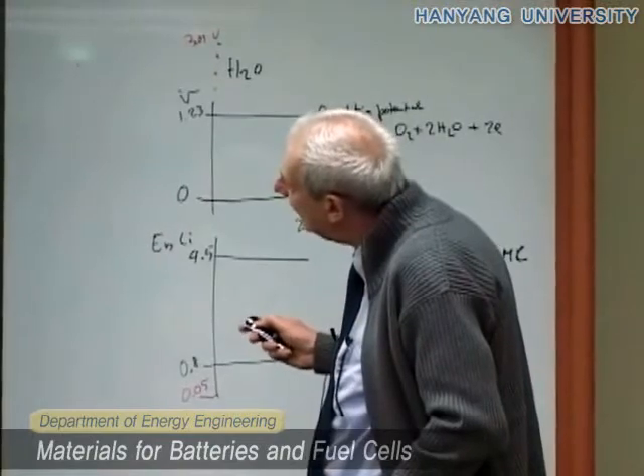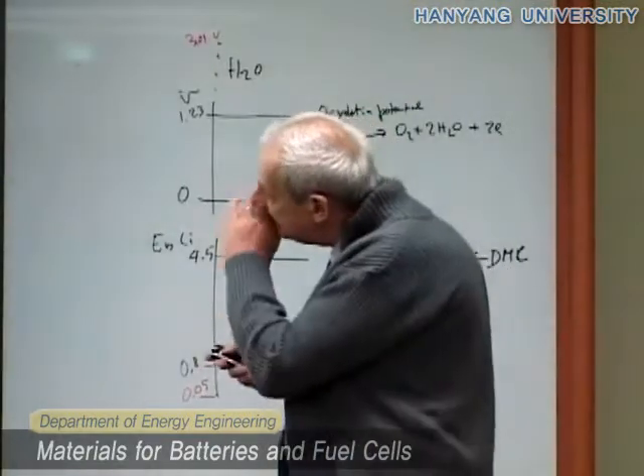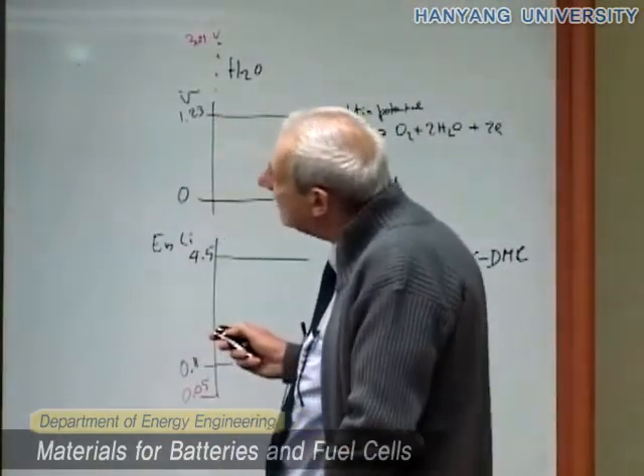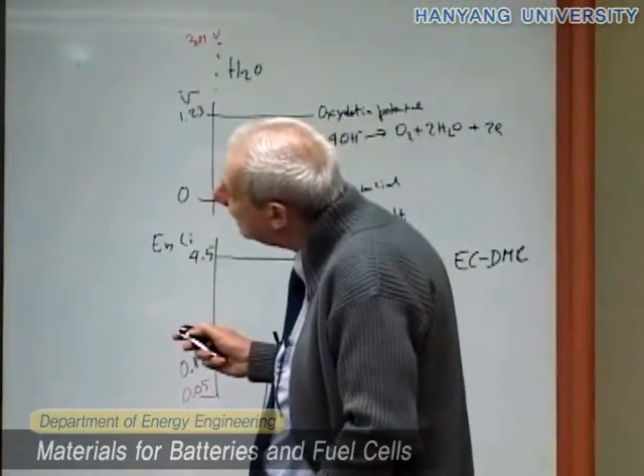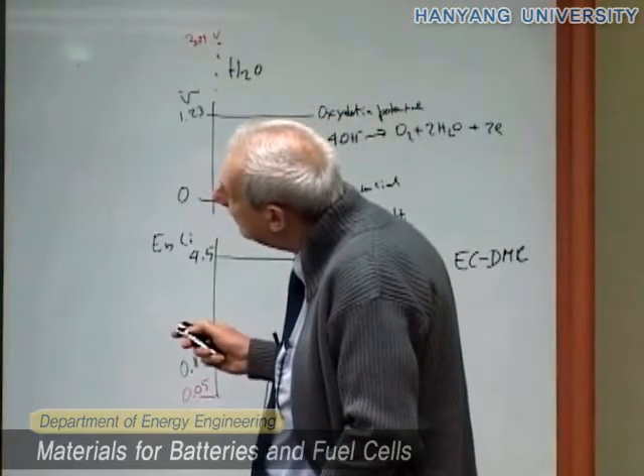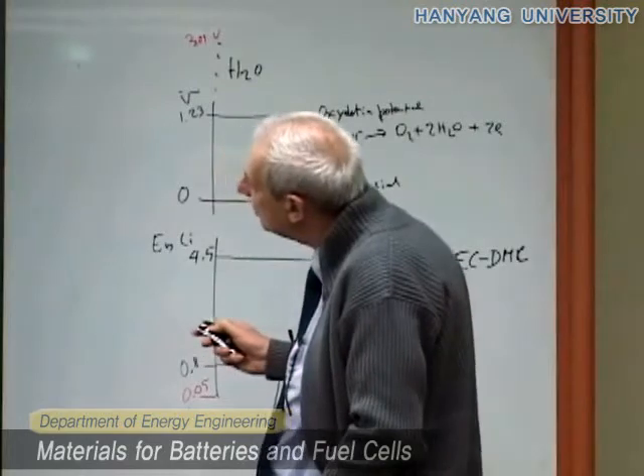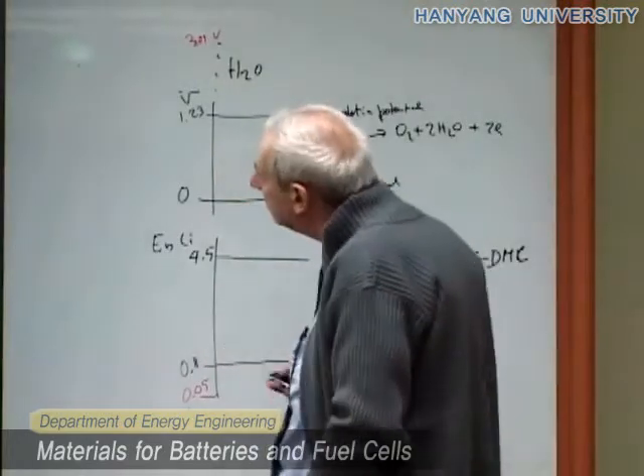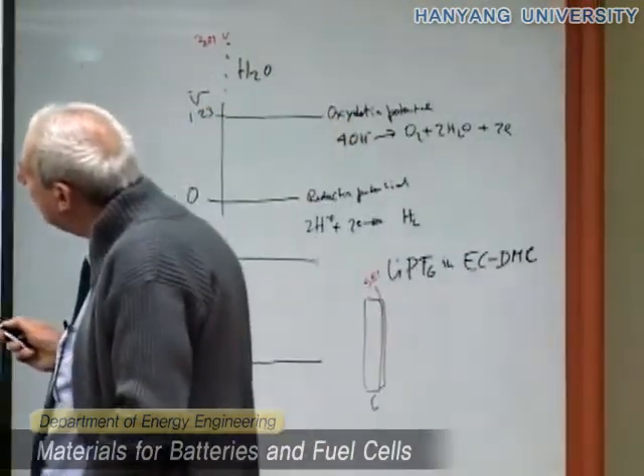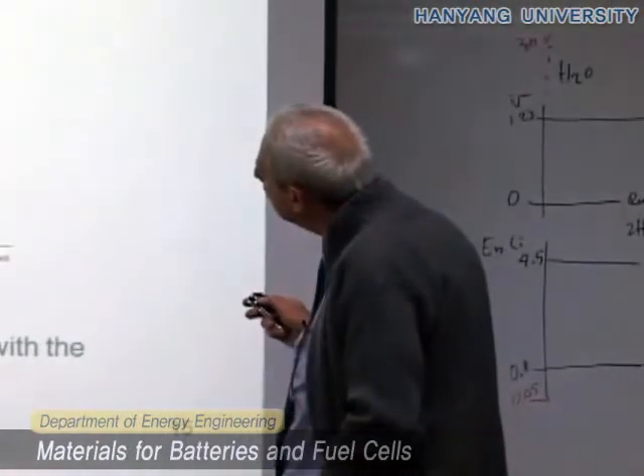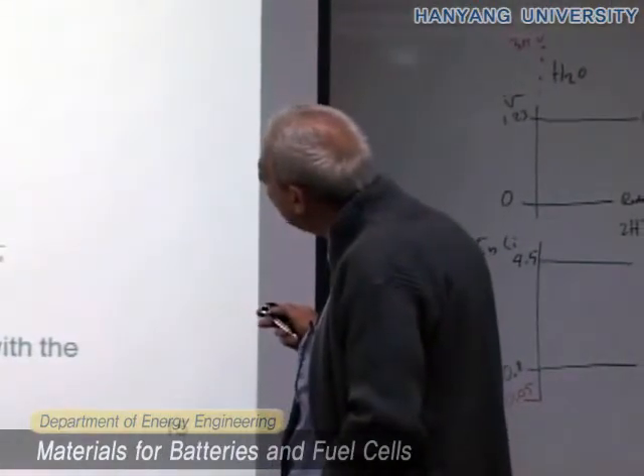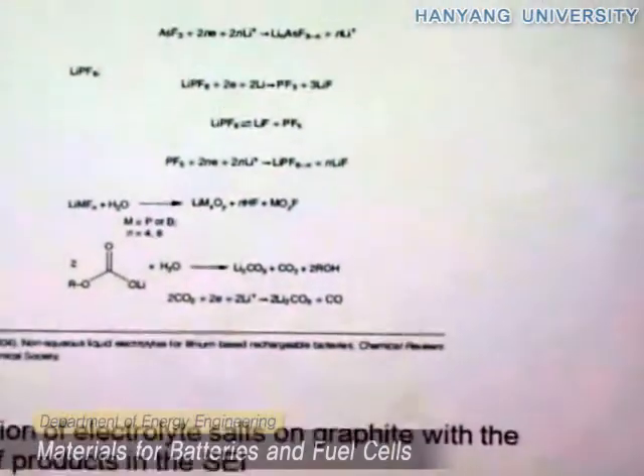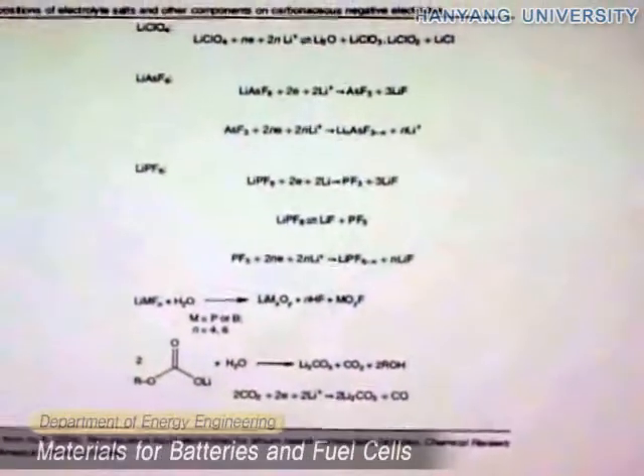The maybe most interesting case for you is this one of lithium hexafluorophosphate, which is the most common salt used in these batteries. And you see that the decomposition can give rise to some fluoride materials. And if you have some water, this becomes HF, which is very corrosive.